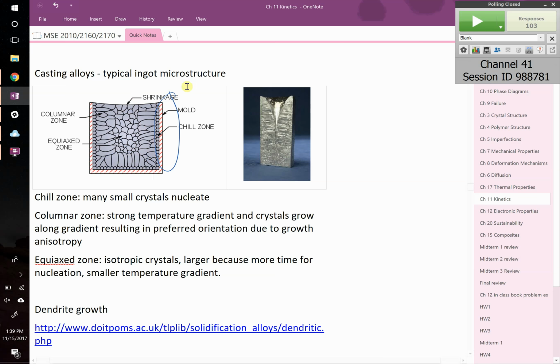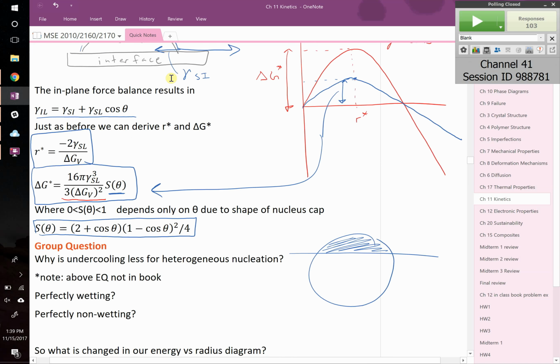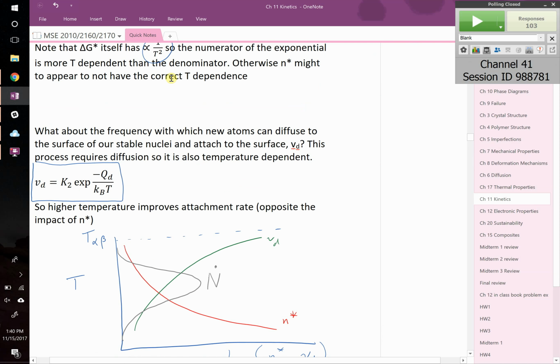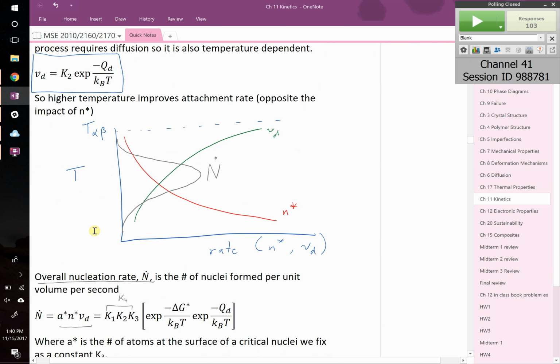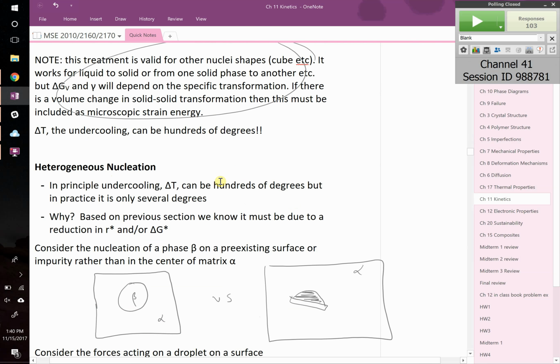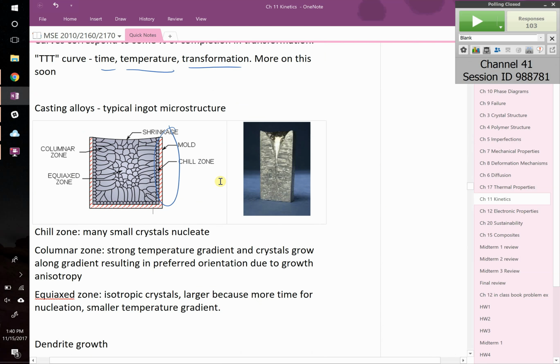Because it's cold, right? If we go back to our drawings, we showed the number of nuclei as a function of temperature. If you're way below the melting temperature, you should have tons of nuclei. So it's going to have lots and lots of little nuclei at the edge that are going to form. And then as you go deeper within the alloy as it's cooling down, you're at a higher temperature where growth is going to dominate. Because of that, you'll see lots of grains at the edge, but some of these will grow more than others as you go towards warmer and warmer regions. And they're going to tend to grow in the direction of the temperature gradient.